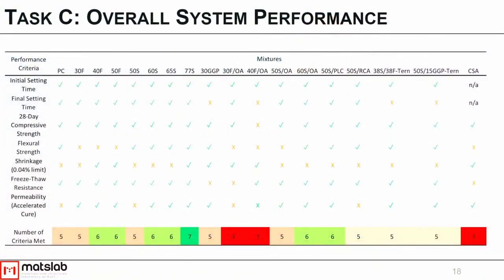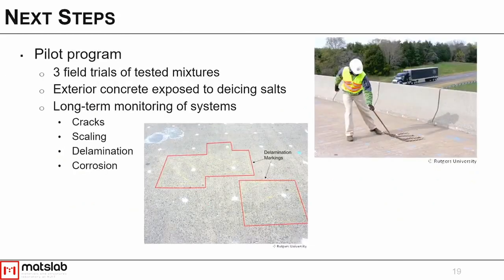And then we had a number of mixtures that met at least 6 out of the 7 criteria. So that kind of gave us our baseline for which mixtures we wanted to start to analyze for doing field testing. We're still finalizing which ones we want to do, but certainly that 77% slag is going to be in the mix. Our next step is going to be our pilot program.